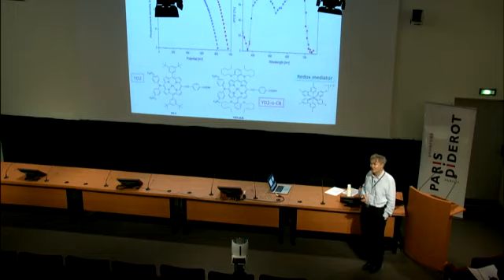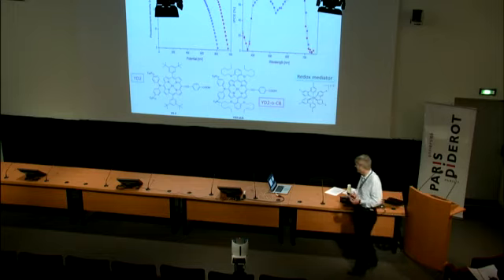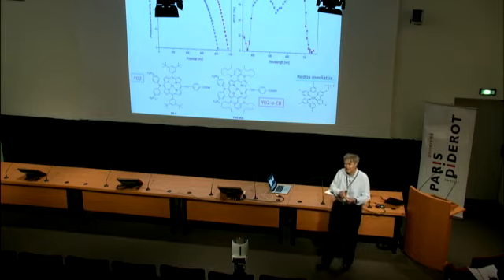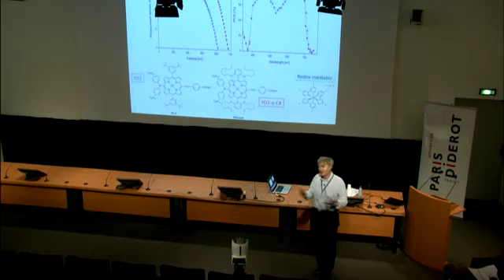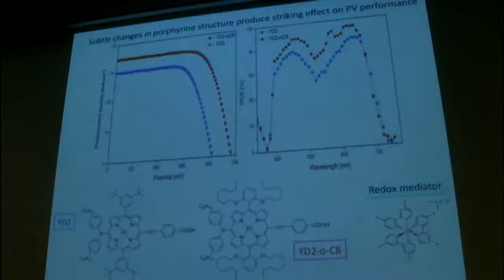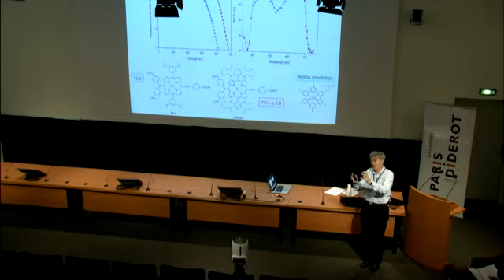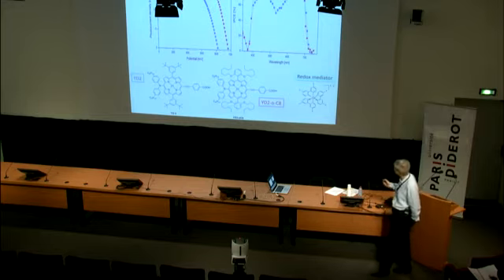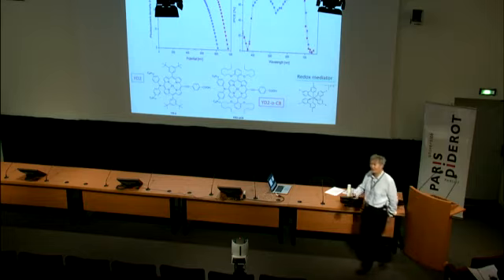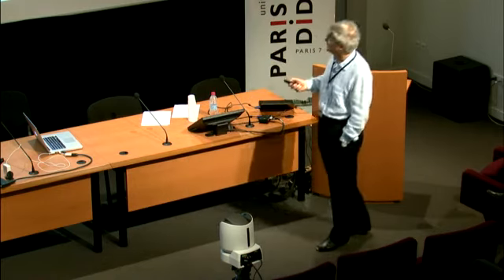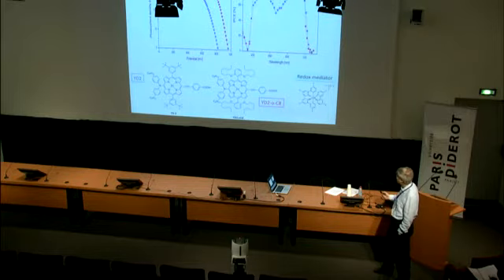And why is that? Well, it's all the interface. I mentioned in the very beginning that the key to the successful operation of this cell is that you have to control the interfacial electron transfer dynamics. What happens with this dye is that, when you draw the three-dimensional structures, you get a very efficient protection of the surface from access of the redox mediator. The redox mediator can't get to the TiO2, where it can back react. It can still regenerate the dye, but it doesn't have to go to the TiO2 surface. So that's why we get this